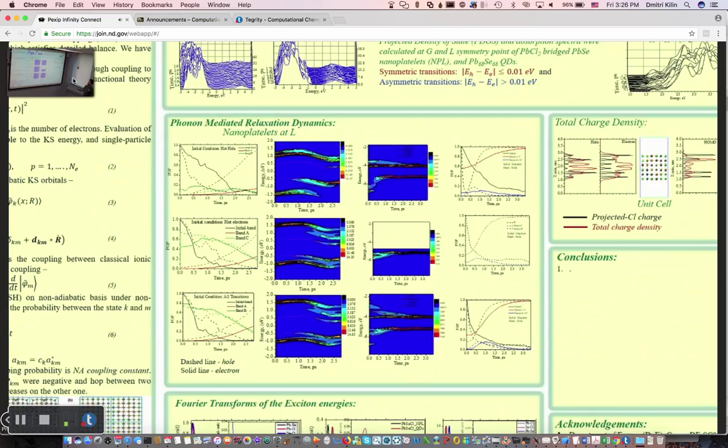And for the other two, red is the band I consider, because if you look on the dispersion curve above the figure, there is a band and a subgap in the electron orbitals. So first four states, and then a small gap and another band. The four states I consider as one band, and this red line indicates that band. The population in that band keeps increasing in this scenario, close to 0.9.